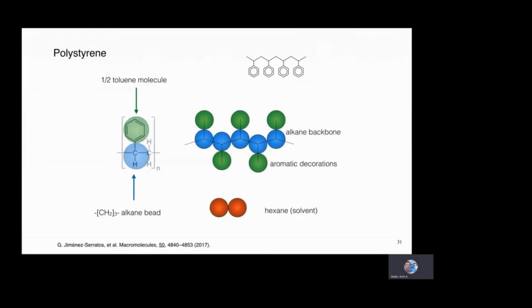Polymers are a classical extension of these ideas. Polymers are, by their own nature, formed by smaller groups, in which each of these smaller groups can be fine-tuned to the properties of either a monomer or the constituent molecules. Atactic polystyrene is a very nice example. Here we used an alkane backbone, which we fit to the alkane molecules themselves, and we decorate this alkane backbone chain with small toluene molecules.